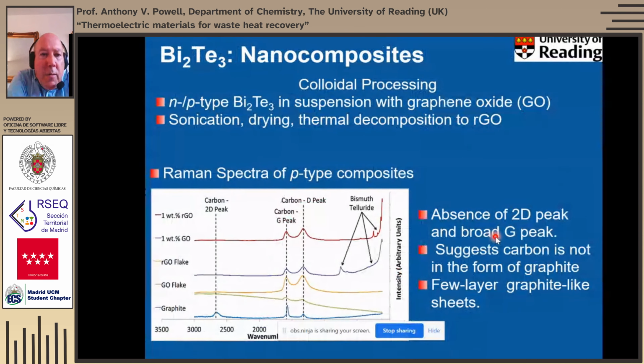So this is some work that we've done very recently. We've not yet even published it, on nanocomposites of bismuth telluride. This is trying to take the current state-of-the-art material at low temperatures and try to improve it. So what we've done is a colloidal processing route where we essentially mix the bismuth telluride with known amounts of graphene oxide. And after some treatment, we do some decomposition of that graphene oxide to reduced graphene oxide. So we introduce essentially a carbonaceous phase that's well distributed throughout our bismuth telluride.